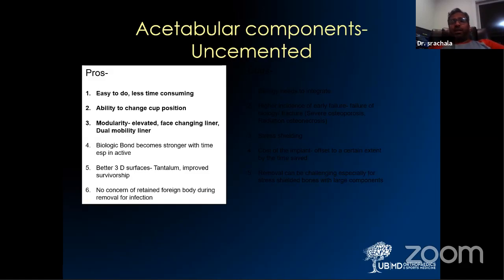Modularity is an advantage. We could use an elevated or a face-changing liner to change the version or abduction. Also, usage of a dual mobility liner in certain difficult cases is also useful. To my knowledge, there's no good cemented dual mobility construct at this point. Again, biologic bond becomes stronger with time, especially in active persons. Just like with fracture healing, over a period of time, the bone remodels and it becomes stronger as long as the bone heals. Better 3D surfaces, like quoted by Dr. Rajkumar, three-dimensional coated is where there's a porous ingrowth surface like titanium, tritanium, tantalum, porocoat. All these have improved the survivorship as opposed to two-dimensional coated surfaces in the acetabulum. On the femoral side, 2D or 3D doesn't matter. On the acetabulum side, three-dimensional coated surfaces have improved the outcome.